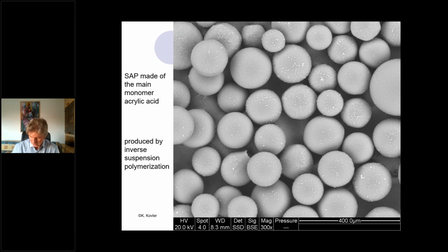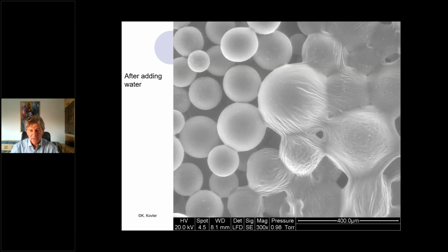These are microparticles. And then we took this picture under an environmental scanning electron microscope, which doesn't require any vacuum. And then we can see how the absorption of water results in the expansion. So particles are expanding. This expansion is very fast, and it can happen in very few seconds after mixing with water.